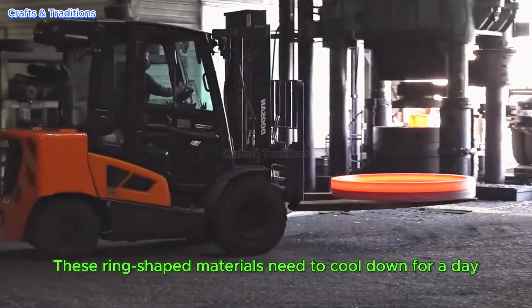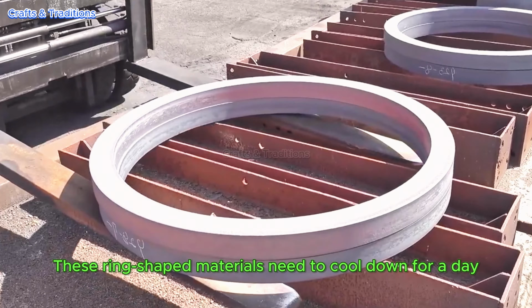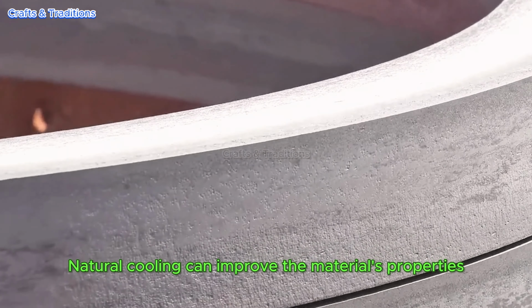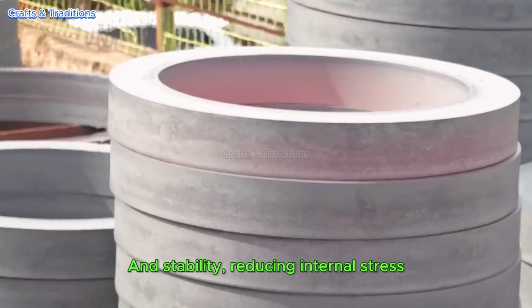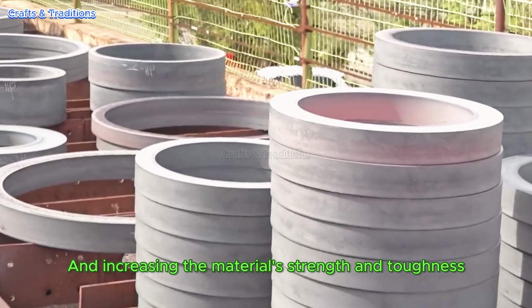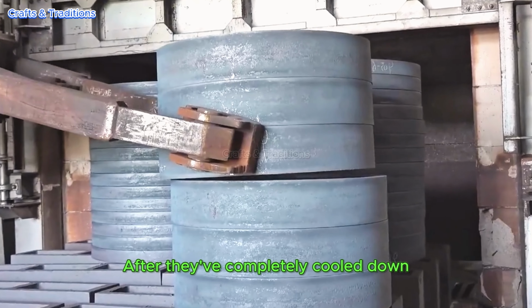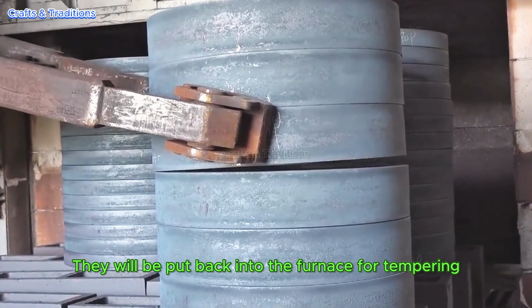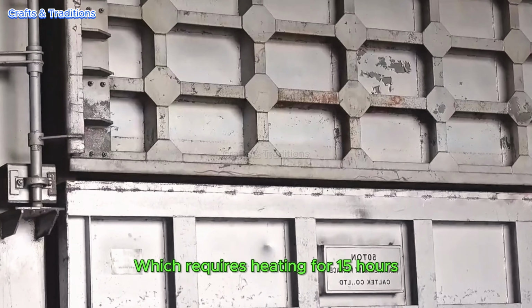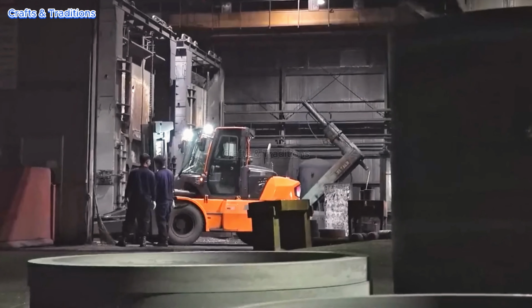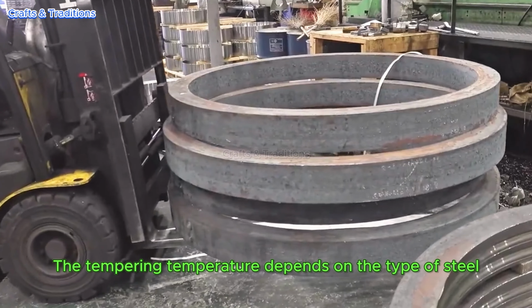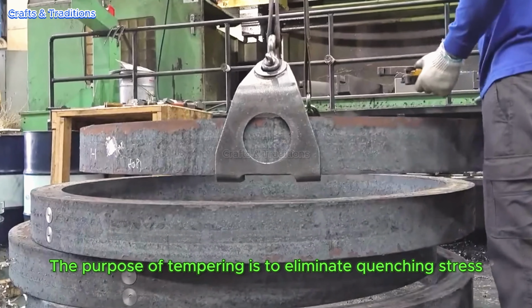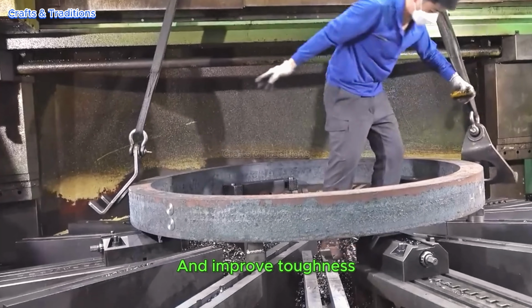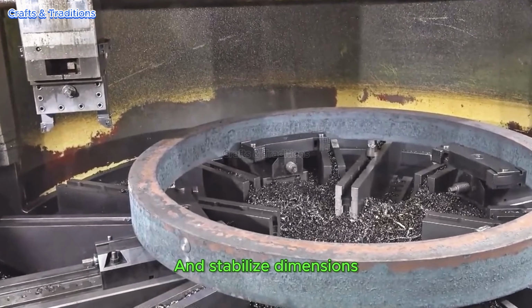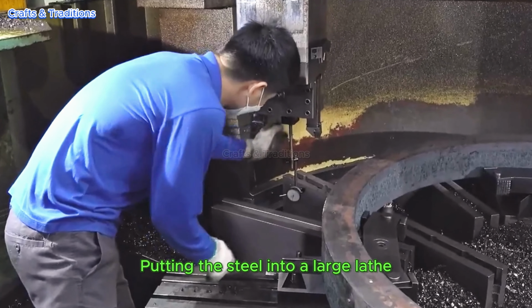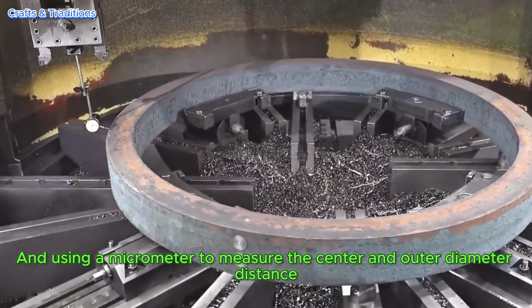These ring-shaped materials need to cool down for a day. Natural cooling can improve the material's properties and stability, reducing internal stress and increasing the material's strength and toughness. After they've completely cooled down, they will be put back into the furnace for tempering, which requires heating for 15 hours. The tempering temperature depends on the type of steel. The purpose of tempering is to eliminate quenching stress, improve toughness and stabilize dimensions.